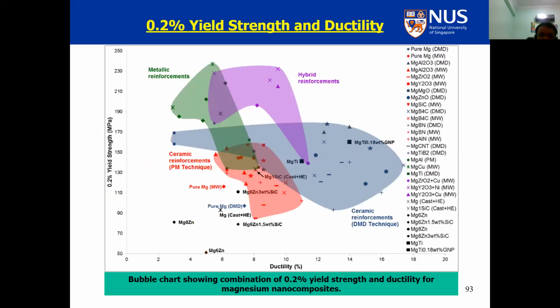So we did a lot of work, and part of the work is summarized in this slide. We used metallic reinforcement, hybrid reinforcement, and ceramic reinforcement. And here's the bubble chart, which also differentiates between the liquid casting method we used, in this gray area, and this bright orange area, which is the powder metallurgy zone. Depending on the strength and the ductility that you want for your application, or the requirement of your application, you can choose a material from this kind of chart.